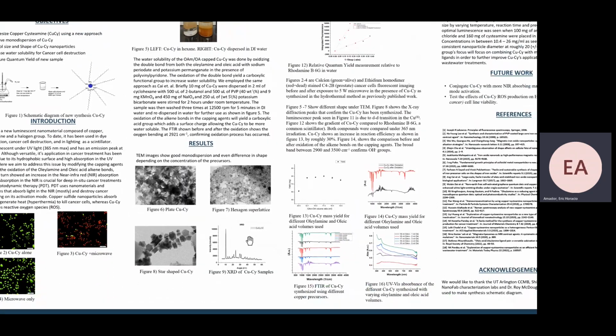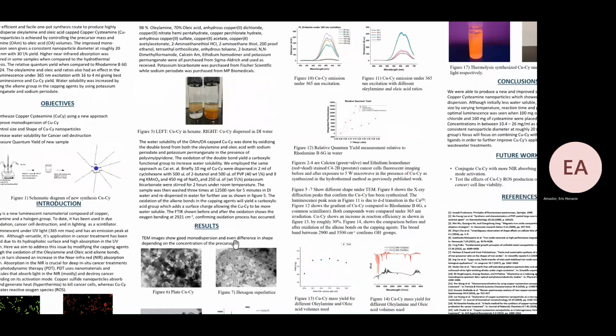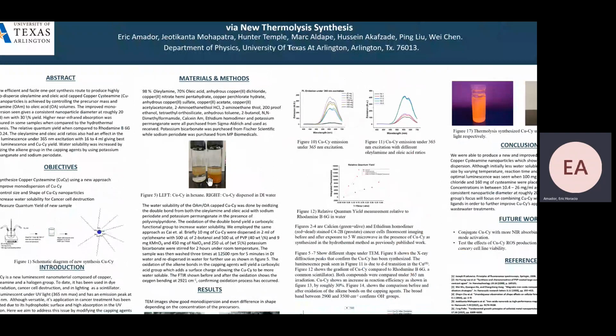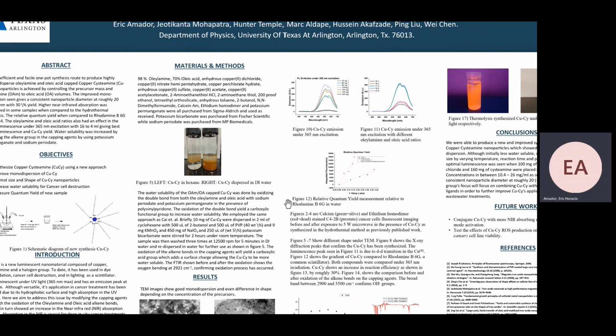And we also found a way to make it hydrophilic, which was to oxidize the alkene bond on the oleylamine and oleic capping agents. And we did this by mixing CuCy or copper cysteamine in an organic solvent such as chloroform, and then adding potassium permanganate in order to oxidize this alkene bond.